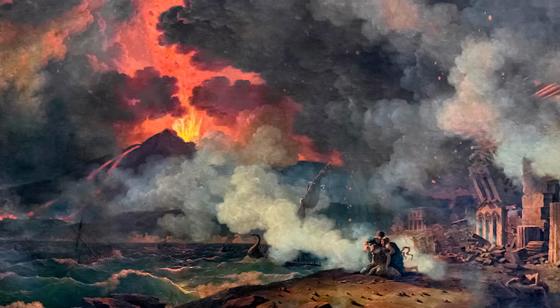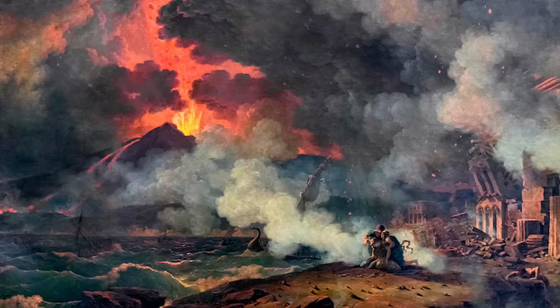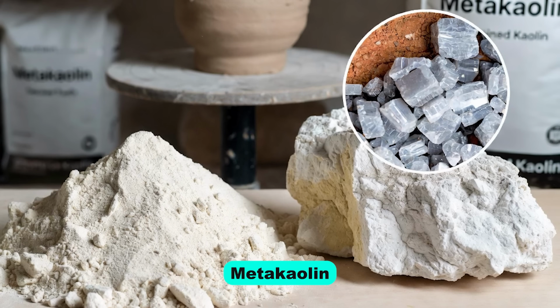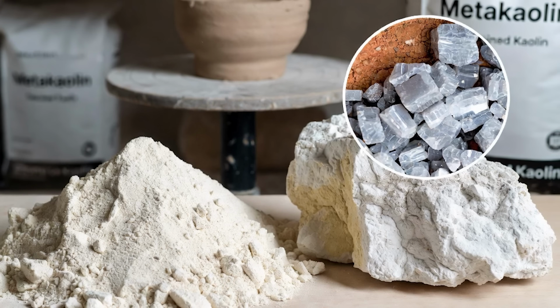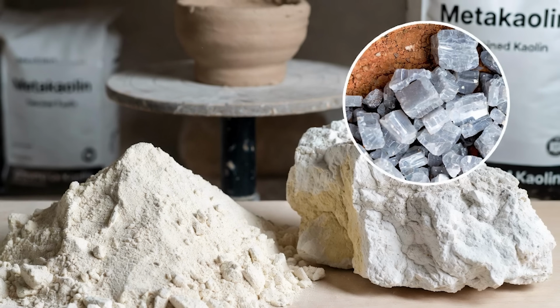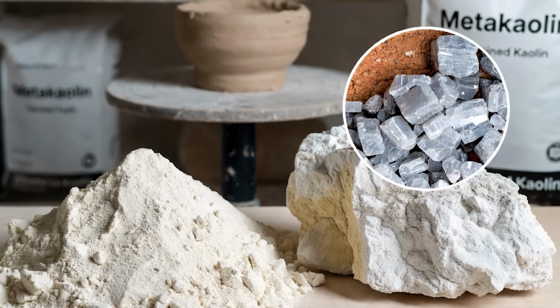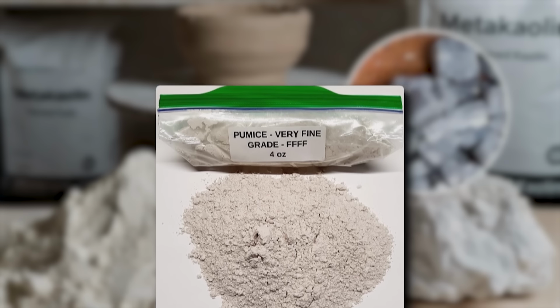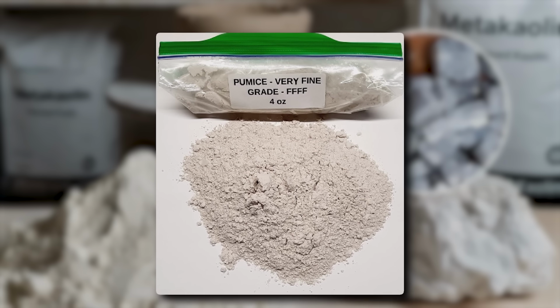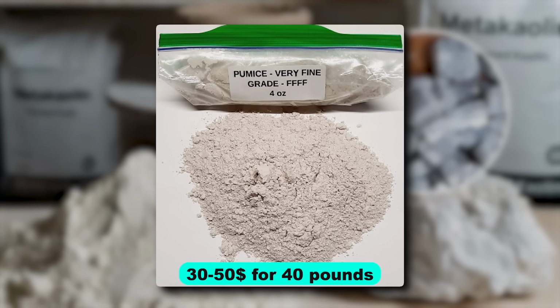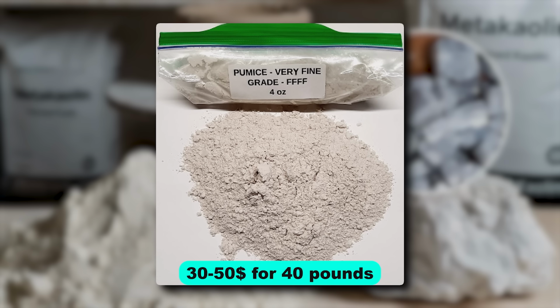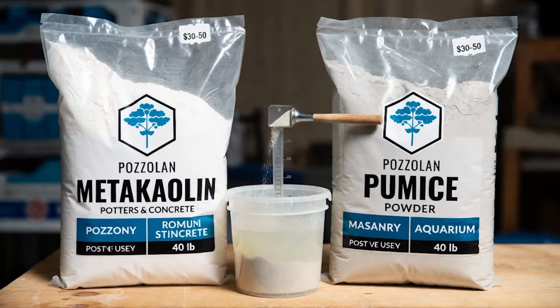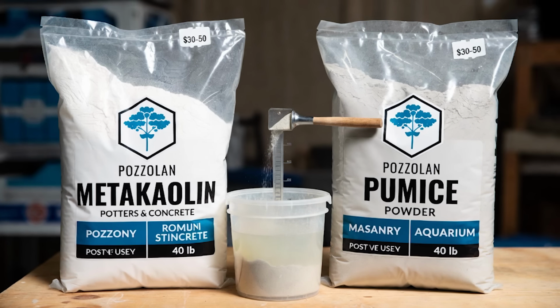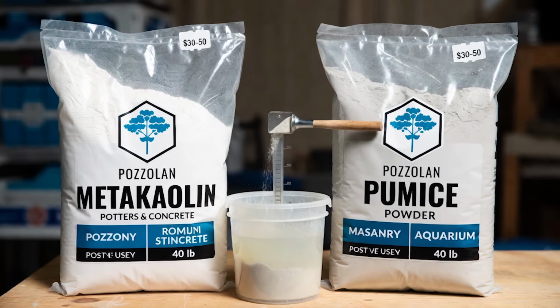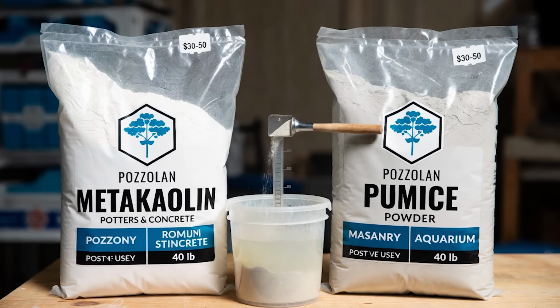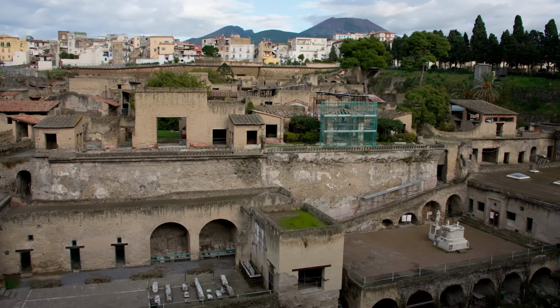You do not need to fly to Pozzuoli to mix this yourself. Metakaolin, the calcined kaolin clay sold to potters, is the cheapest and most reliable substitute. Pumice powder from a masonry or aquarium supplier works just as well. $30 to $50 for 40 pounds. 1 part by volume in your mix. That single ingredient does what Portland cement cannot. Bay of Naples ash worked.